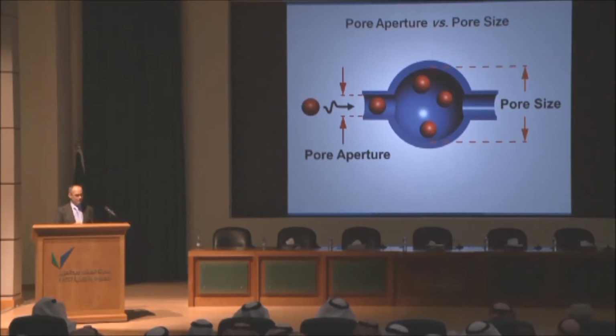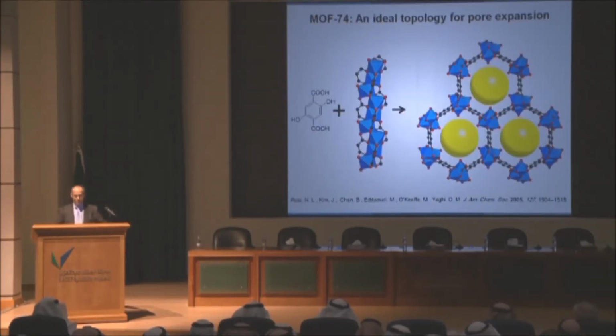And so now I'm going to show you another huge challenge that we've been able to address. In porous materials, the chemistry that you do in the pore has a lot to do with what can go through the pore or what can go through the opening. So if the opening is small, you can only operate on small molecules. If the opening is large, then you could use large molecules. In fact, maybe you could use proteins and other. So it's always been a challenge to open the windows or the doors that allow you to enter into the pores. And so we chose one of these MOFs to illustrate the point. And I'm not going through necessarily and explaining the challenge in great detail, but only to say that it has not been easy to open up the pores, because when you open them up, the structures collapse or something happens like that. But it turns out that if you choose the right structure, then they don't collapse, and in fact, you make very stable materials.